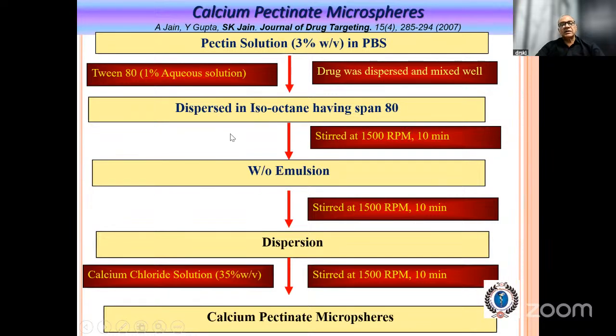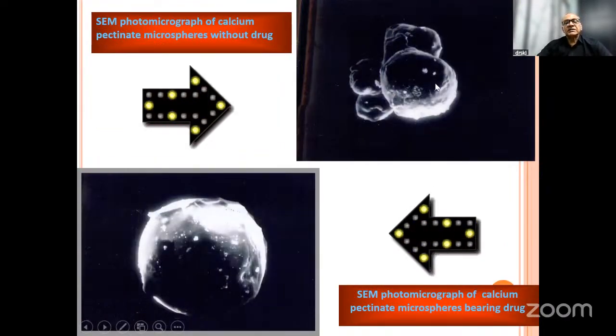The whole emulsion is stirred at 1500 RPM for 10 minutes. We'll get a water-in-oil emulsion, and the water globules are the pectin globules, right? Stir this emulsion further for 10 minutes. To this dispersion, we add calcium chloride solution dropwise, so that the calcium ions react with the pectin and we get calcium pectinate, which is solid in nature and insoluble in water, right? So we get the calcium pectinate microspheres; separate them and wash with water. This is the photograph of the calcium pectinate microspheres without drug.